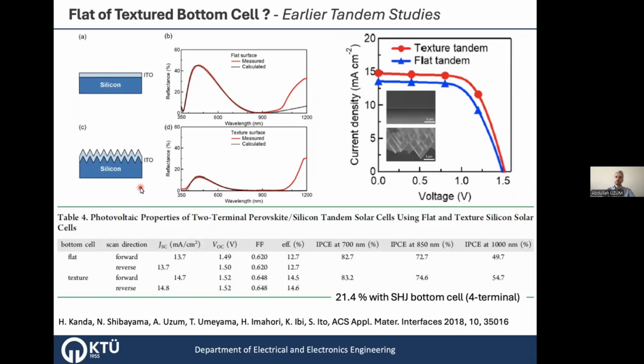But texturing helps for the mechanical stack, or if the top layer filters. And if you have 4-terminal, or 2-terminal mechanical, it is an advantage. With this structure, for example, with the 2-terminal device, we had 14.6%. If we use silicon heterojunction as the bottom cell, which is highly efficient, and the 4-terminal, we could achieve 21.4% efficiency.